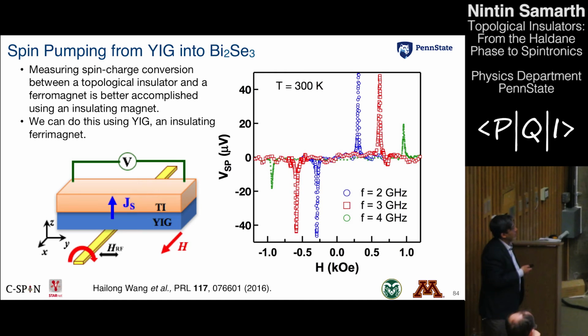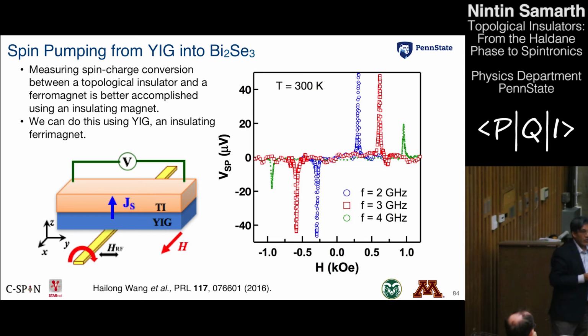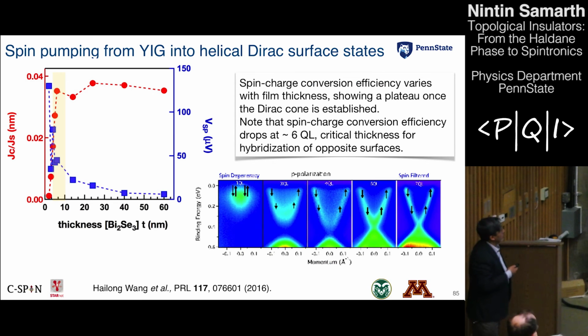And as you sweep your magnetic field and measure a voltage, you get these resonance peaks that correspond to the ferromagnetic resonance of the ferromagnet. And by analyzing this kind of data, you can pull out the spin to charge conversion efficiency. And we can now measure the spin to charge conversion efficiency. This is put in units that I'll explain in detail later if you're interested. But we measure it as a function of the thickness of the topological insulator. And what you find is that as you change the thickness of the topological insulator from a nanometer to something like 60 nanometers, that spin to charge conversion efficiency plateaus just as you reach a thickness where this Dirac point becomes intact, right? So what we see is a clear correlation between the formation of the Dirac cone and the stabilization of this spin to charge conversion efficiency.